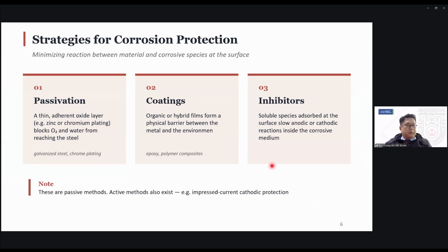Okay. So the main strategies we normally deploy, there are three types. You can have a passivation method, you can have coatings, or you can also introduce inhibitors. In passivation, this is what you see maybe in galvanized steel and stainless steel. In galvanized steel you add a passive layer. In stainless steel you normally add chromium, so then they will form these chromates that actually passivate the surface. But some of these techniques generally can be more expensive.